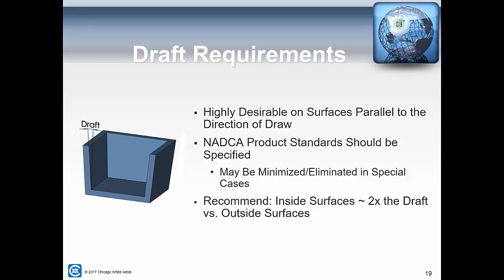NADCA, the North American Die Casting Association standards, does do a very good job of highlighting the areas that should have draft and what kind of factor that should take part in your part design. It is very part dependent. Some geometry, depending on how deep a boss or cored hole is, should have different degrees of draft on it, whether it should be a high degree or low degree. In some special cases, depending on the part size and where it's located, some areas can have the draft eliminated completely. But as a general rule of thumb, it is recommended that all inside surfaces have about 2 times the draft that outside surfaces of the part does.